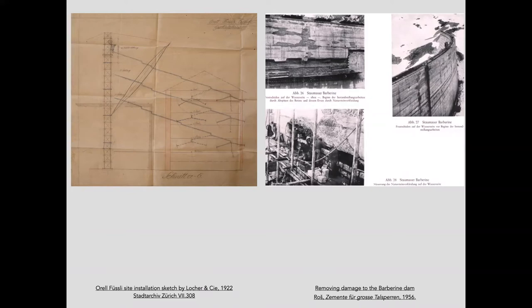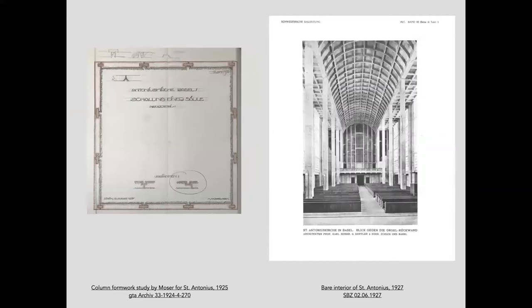So this enthusiasm for wet mix concrete suggests that the notion of flow was so powerful that it threatened to supersede other deeply valued qualities of concrete, since this wetter mix, with more water, was known to both reduce strength and durability. And so after these accidents, the notion of pouring concrete didn't disappear, but rather it was enacted through other means, replaced with plasticizers and pervibrators that could induce flow in other ways.